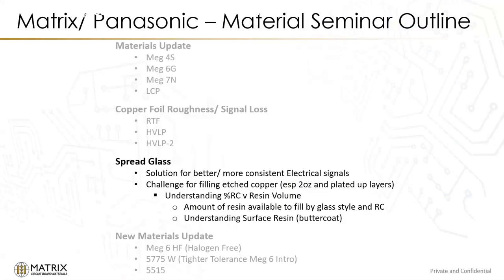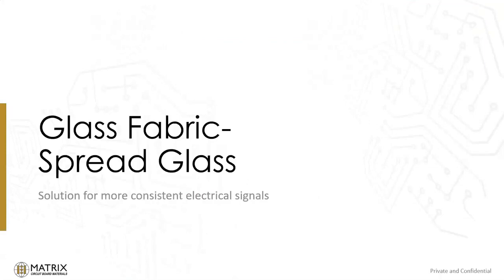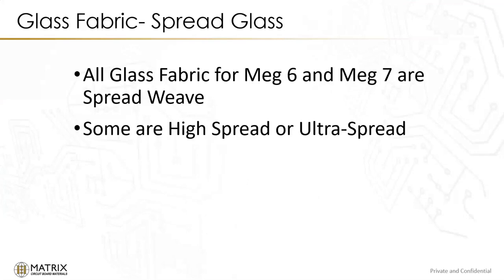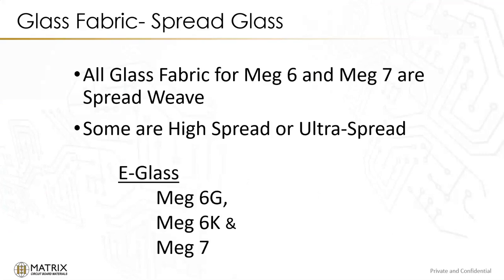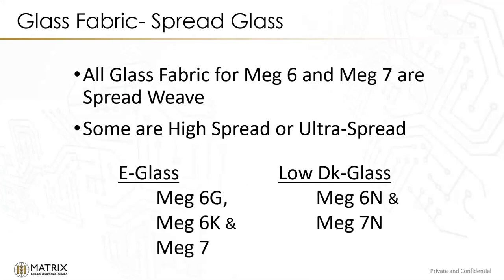So we move into the glass. Over the years, we've been talking about spread glass, and I think spread glass was really developed for the laser microvias initially, trying to make it more ablatable. Then the electronic designers got a hold of it, and it actually provides a little bit better solution for that. So all the fabric that's used for Meg 6 and Meg 7 is spread glass. They're spread weave. And there are some that are actually high spread or ultra spread that are used with it. And that applies both with the E glass, with the Meg 6G, the K, and the 7, and also with the low Dk glass, Meg 6N, Meg 7N.